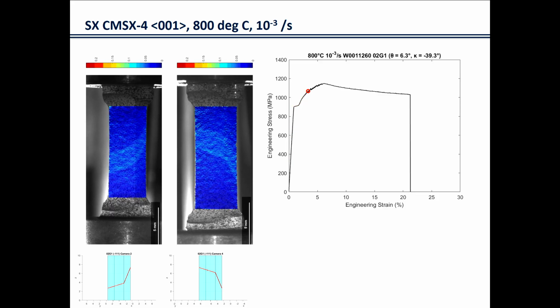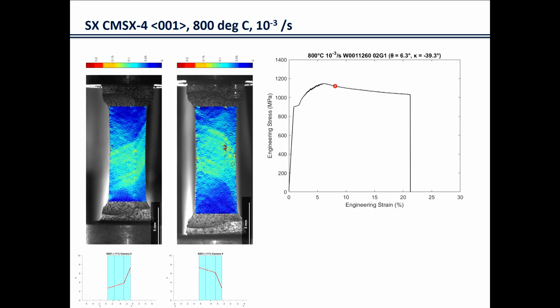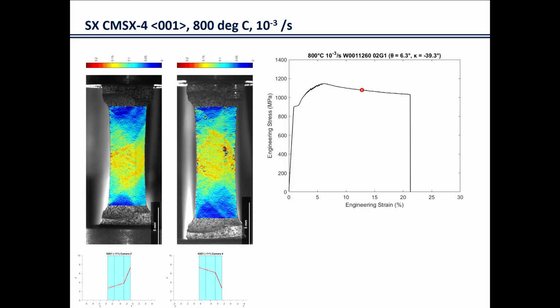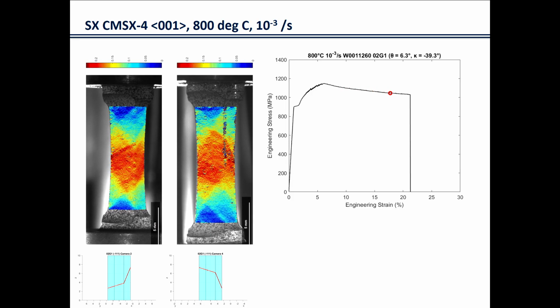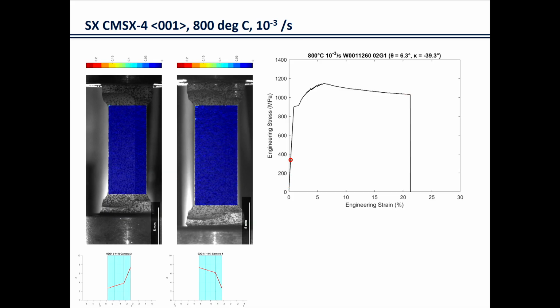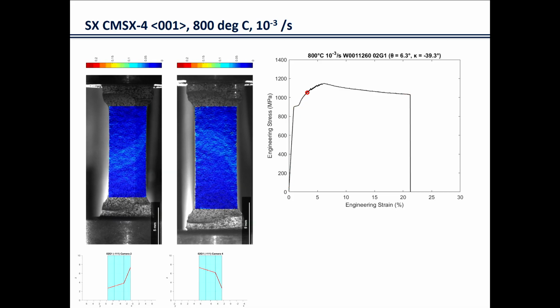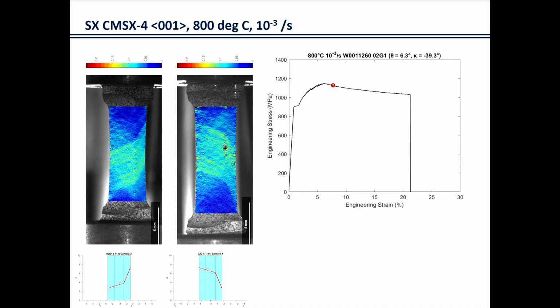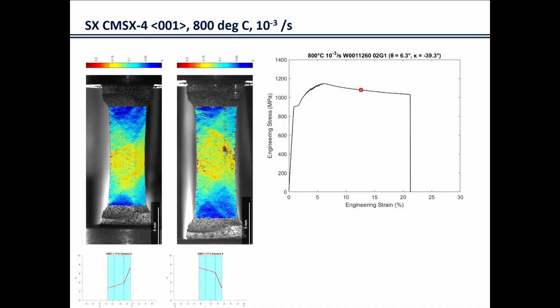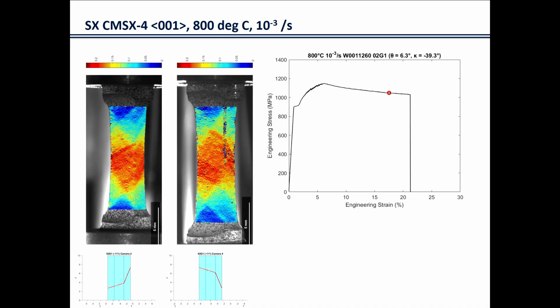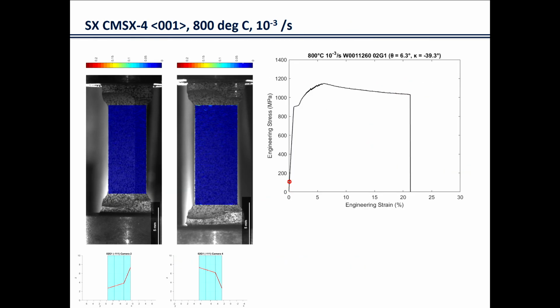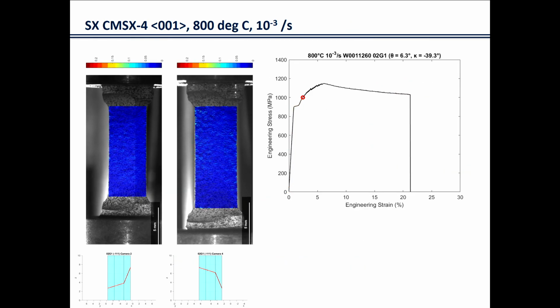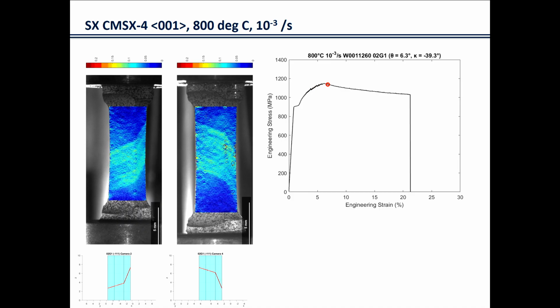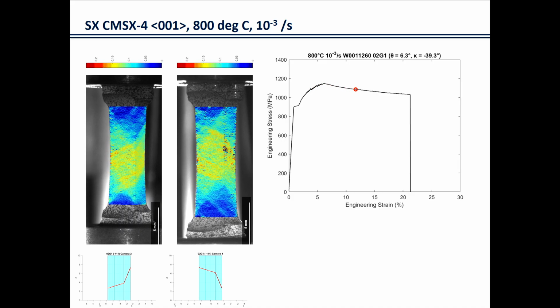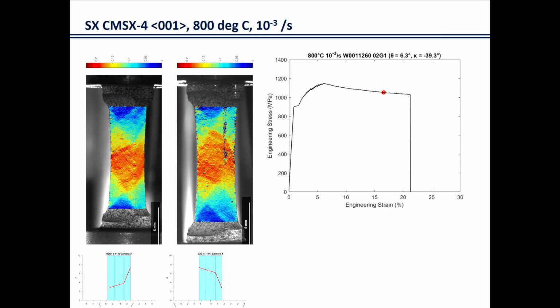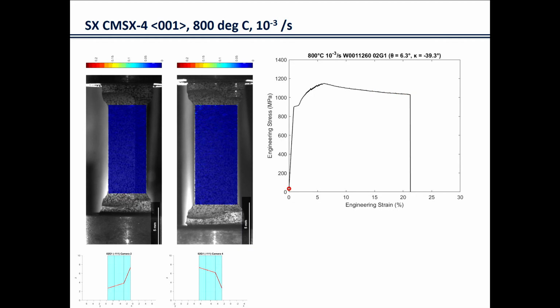Here's another example fresh off of the press. I think these measurements were only made last week in my laboratory. You can see here that this is a stress-strain curve. This is actually a rectangular cross-section. And with the camera-based systems, you can see the strain. You can actually see the strain banding. I'll show it again. You can see here the strain banding occurring in this material over time. So the plastic deformation is clearly not isotropic. There are certain planes on which this material actually is deforming preferentially.